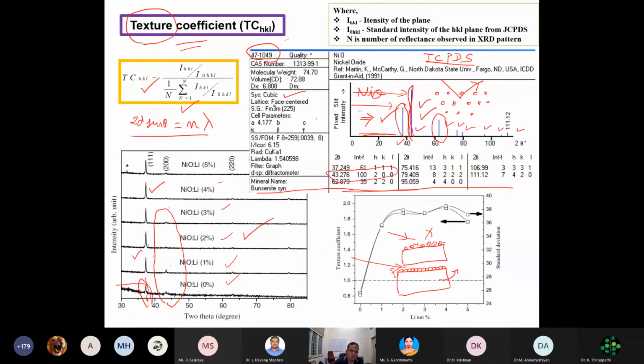So use this formula and plot that particular formula as a function of your variation, whether it's a concentration variation, whatever it is. If your texture coefficient value is less than 1, then it is a polycrystalline material. There is no preferred orientation. Suppose your texture coefficient is more than 1, like 1.4 or 2 or 3, then it is a textured growth. So this is very important for thin films.